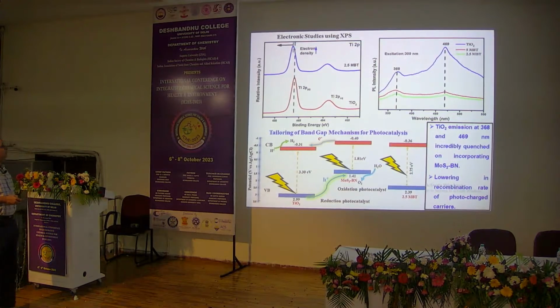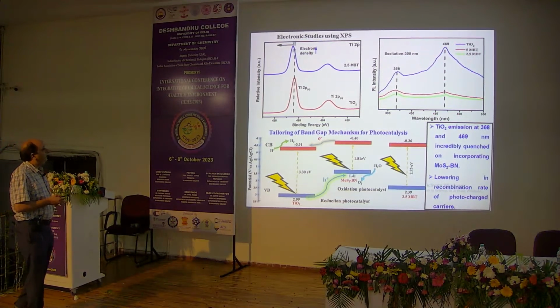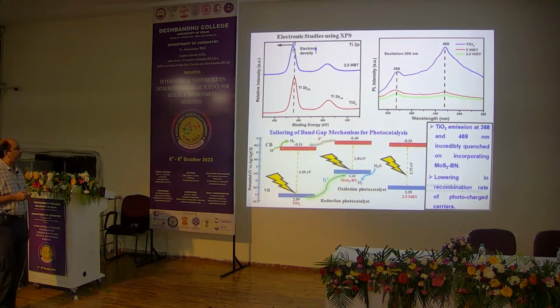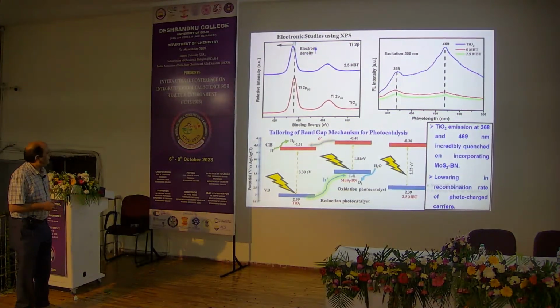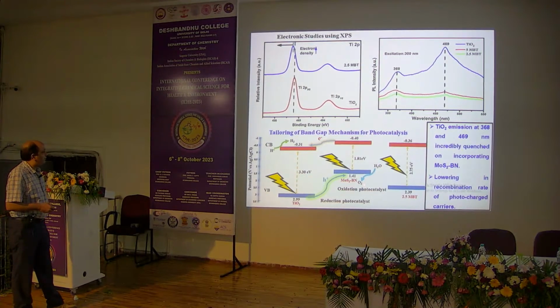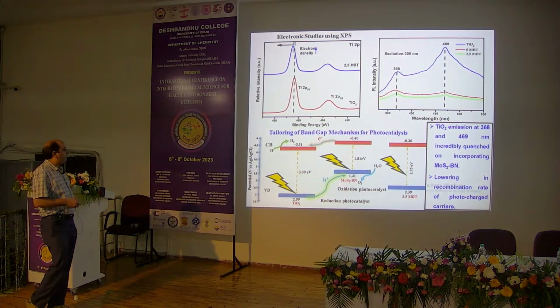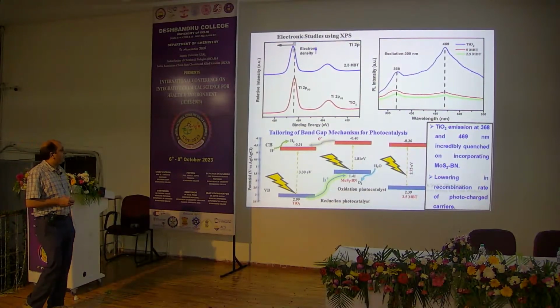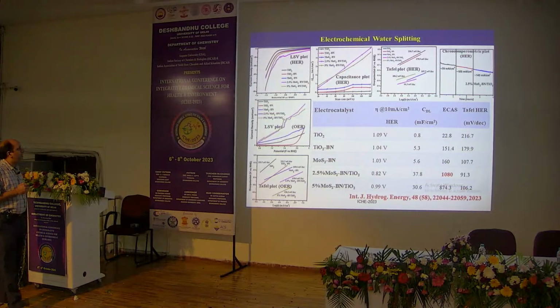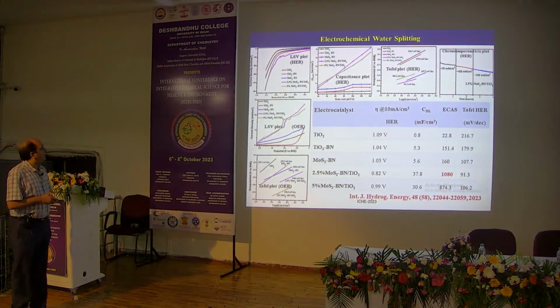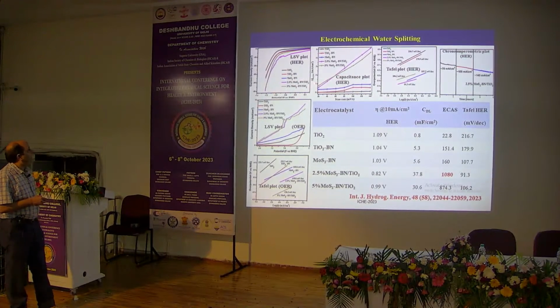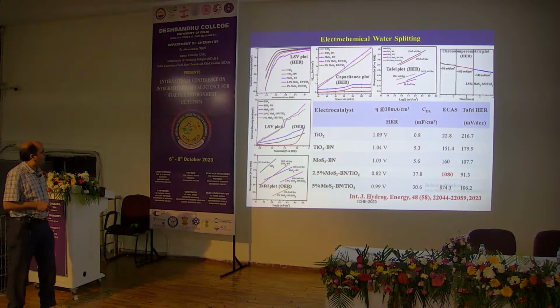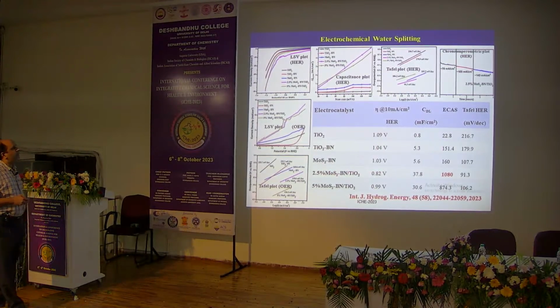And this is the XPS spectra, the peak shift on the left hand side and the decrease in the PL intensity could lead to the lowering in the recombination of the photogenerated charge carriers. And this is the band structure of the TiO2, and this is for the MoS2 boron nitride, the binary heterostructure, and this is the band structure for the ternary phase of the MoS2 boron nitride with TiO2. These are the electrochemical investigations, and it shows that the low onset potential and the low overpotential of the 2.5 MBT, meaning 2.5% loading of MoS2 boron nitride over TiO2, can give the significant result.